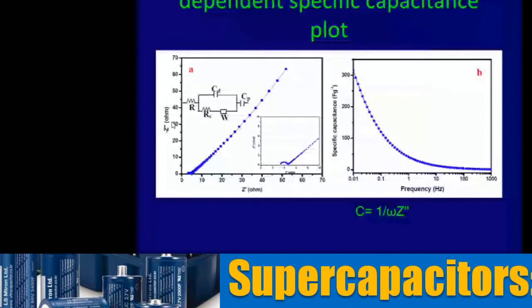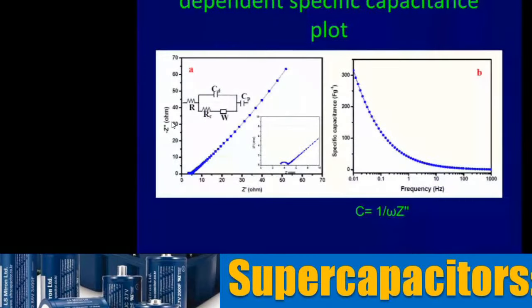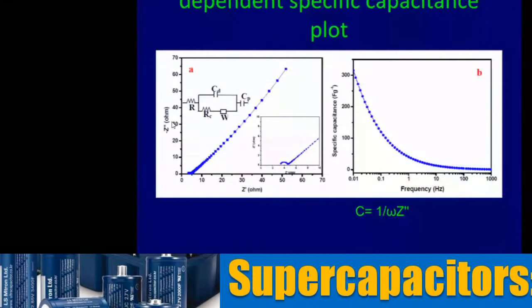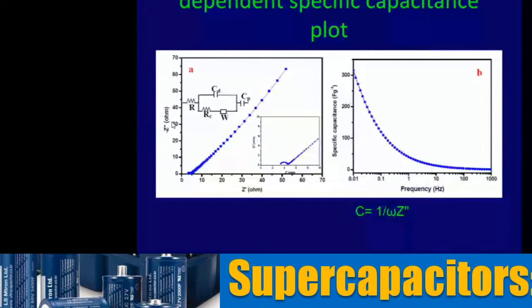So when we see the thing, again with the impedance spectroscopy, we see that with frequency the capacity decreases. The reason is the same. At low frequencies, the potential is increasing slowly. The electrolyte and the electrode find enough time for accepting the charges. At high frequencies, the potential changes at a faster rate. Probably people who have studied dielectrics would know that every dielectric has its own response, and there will be a loss when the frequency increases.